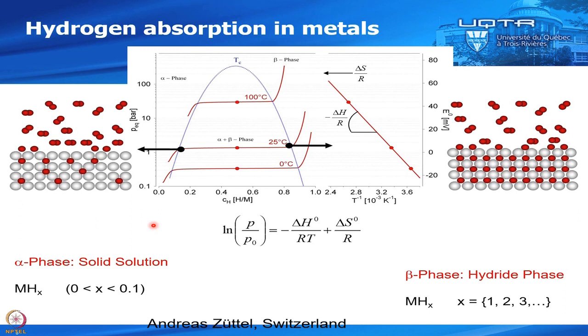And now that you have a new phase in your system, by the Gibbs law, if you have a new phase, it means that you are losing a degree of freedom. So if you are losing a degree of freedom, it means that the capacity could increase even if the pressure doesn't increase, because as the pressure tries to go up, you have more hydrogen that will go into the metal hydride, that will form the metal hydride. So on this plateau, you go from 100% metal and 0% hydride up to here, where you have 100% metal hydride and 0% metal. And here it's 50-50, okay? So you have the transformation along that plateau, from the metallic state to the metal hydride state.